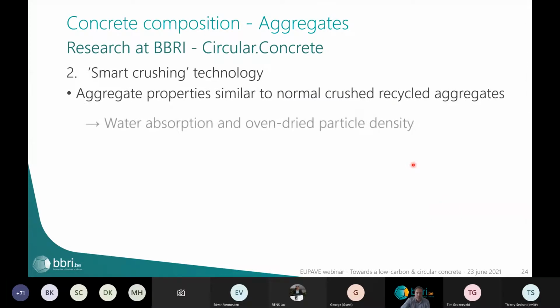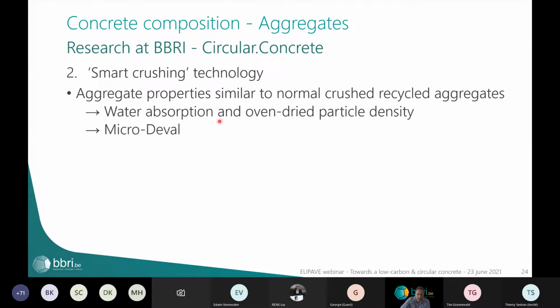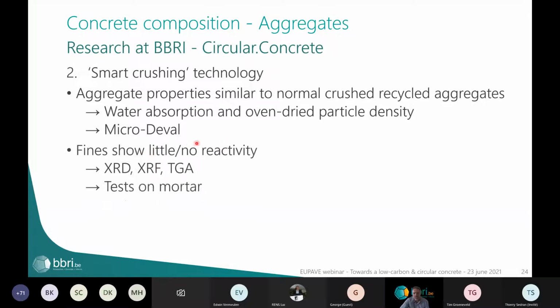What we did was in fact that we looked at the properties of the smart crushed recycled aggregates, and we saw in fact that the water absorption and also the micro-Deval, so the mechanical resistance of these aggregates, were very similar to normal crushed recycled aggregates. So in fact, the smart crushing technology that was used here with these aggregates did not add a lot of value concerning the properties of the crushed recycled aggregates.